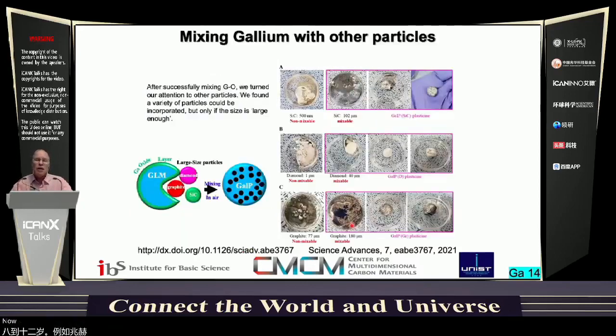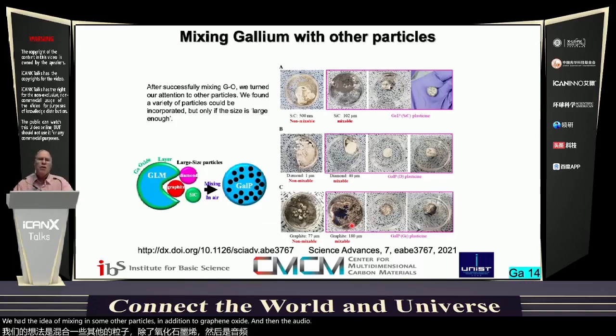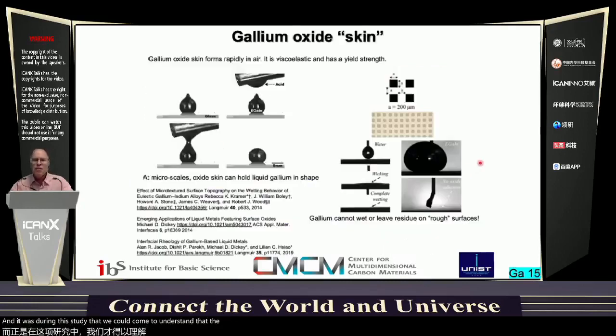Now, we had the idea of mixing in some other particles in addition to graphene oxide and then the RGO. So we tried silicon carbide and diamond and graphite particles themselves. And it was during this study that we came to understand that the size of the particles plays a role. And the reason why this mixing happens at all is because of this thin